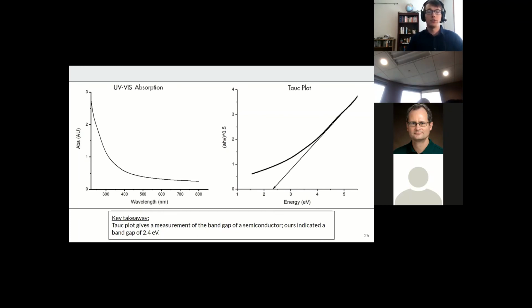The Tauc plot shows the photon energy on the x-axis here, and the quantity (αhν)^0.5 on the y-axis, where α is the absorption coefficient and hν represents the photon energy that was absorbed. The exponent denotes the nature of the band gap transition, and a factor of 0.5 denotes an indirect allowed transition.